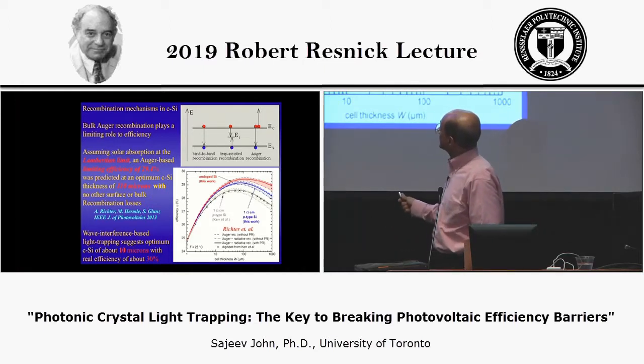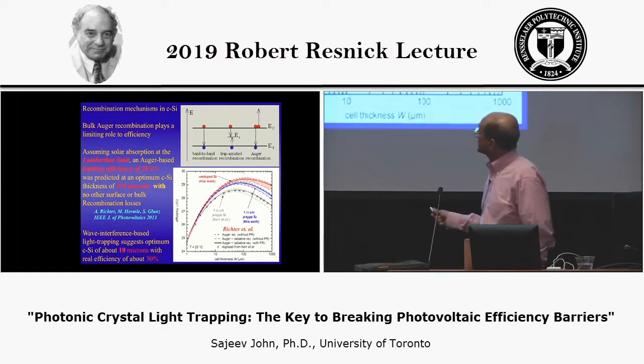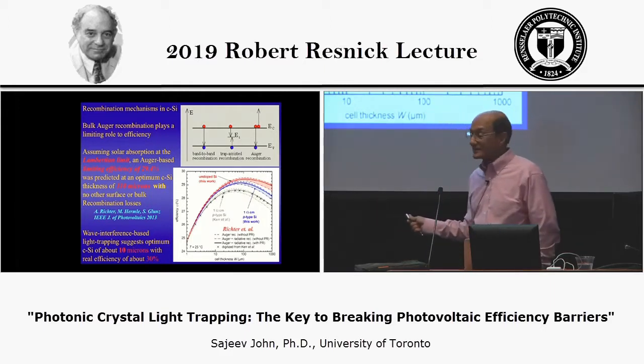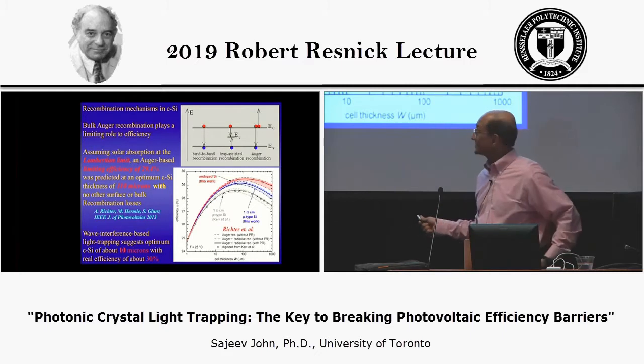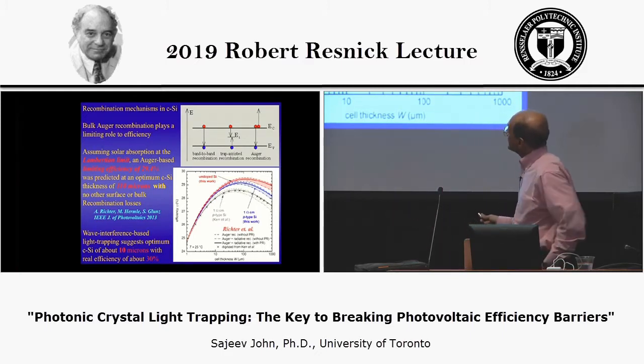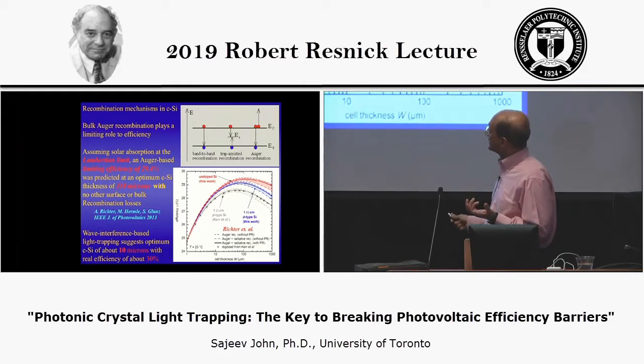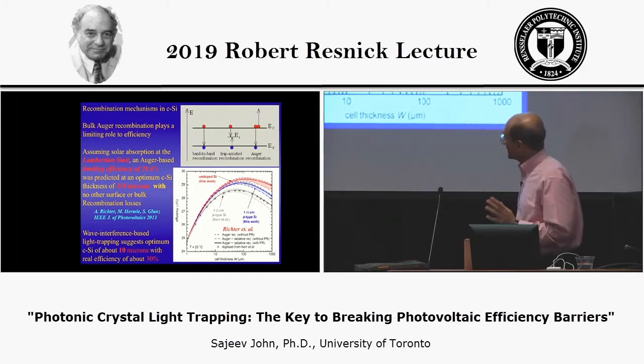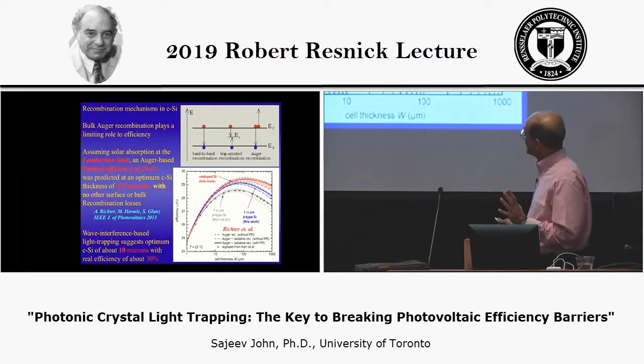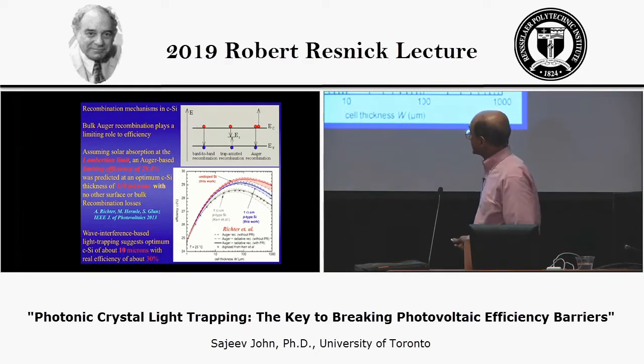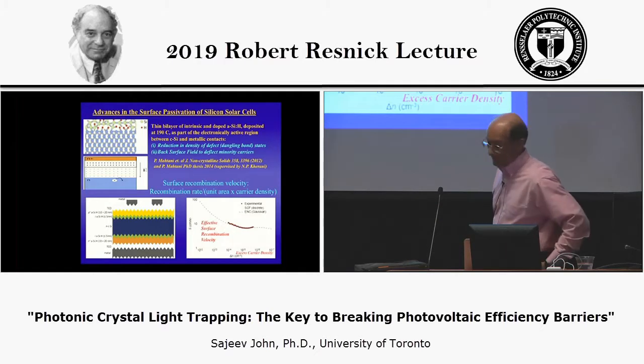And they also declared that based on the Auger limit, as it's called, you can't avoid this type of recombination, that no silicon solar cell could exceed an efficiency of 29.4%. That's already less than the Shockley-Queisser limit. But what they assumed is that the maximum amount of light that you could absorb is defined by the Lambertian limit. And what we'll be showing is that with wave interference-based light trapping, you can exceed the Lambertian limit. And in fact, the optimum thickness is much less than 110. It's probably closer to 10 microns with an efficiency that exceeds this Auger limit, which was based on the Lambertian limit. So that's what I'll be trying to discuss with you.